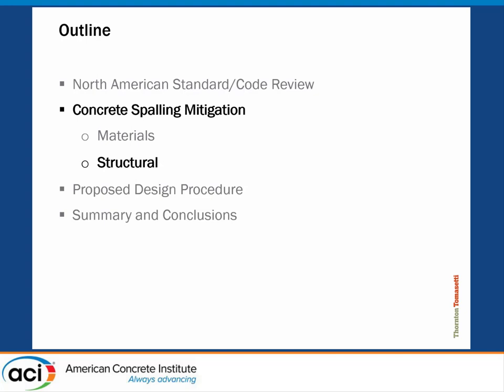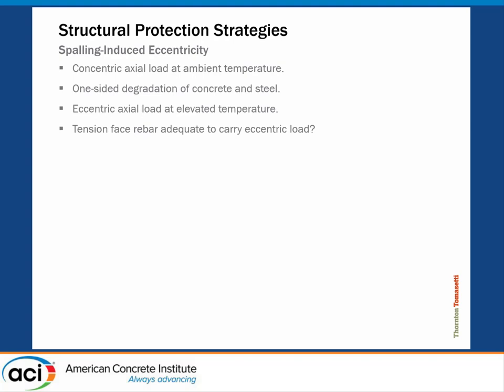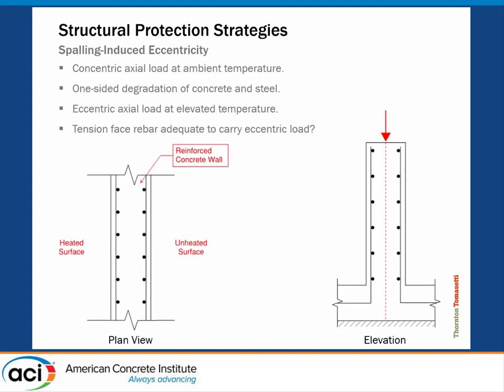From a structural standpoint, even if we mitigate the risk of concrete spalling as much as possible through mixture optimization, you could still have spalling. So there are things we can do structurally: if spalling does happen, let's cover the loads induced by spalling up front. The first is spalling-induced eccentricity. For a standard concrete wall with a one-sided fire, you get unsymmetrical degradation of concrete and steel. The fire-exposed side loses significant strength and the rebar degrades, while the unheated surface is perfectly fine. But the axial load becomes eccentric to the original cross-section from ambient conditions.